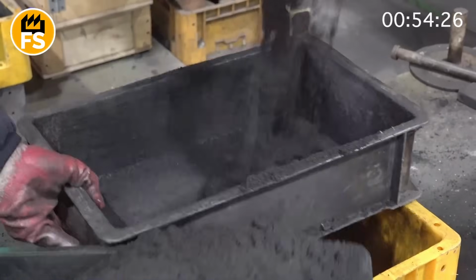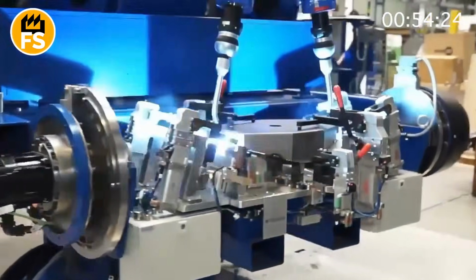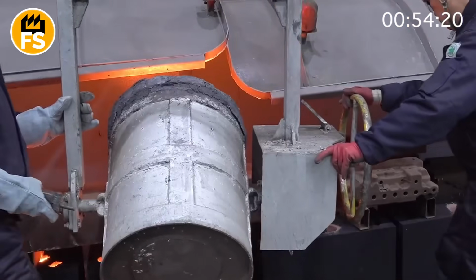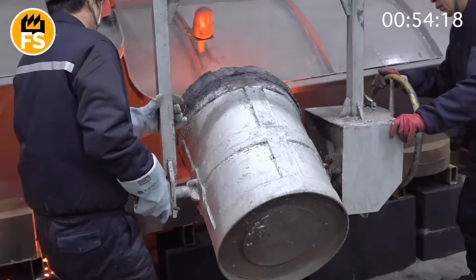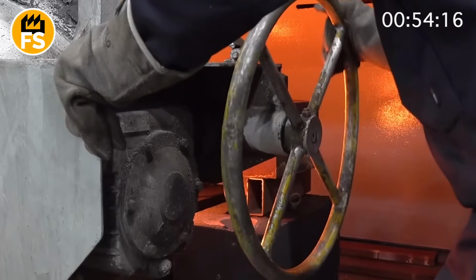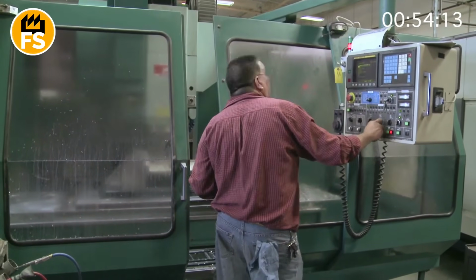A venting and gating system ensures air displacement, otherwise voids will form. The metal cools in the mold for 30 seconds to 1.5 minutes, after which the mold opens and the casting is sent on for further processing.